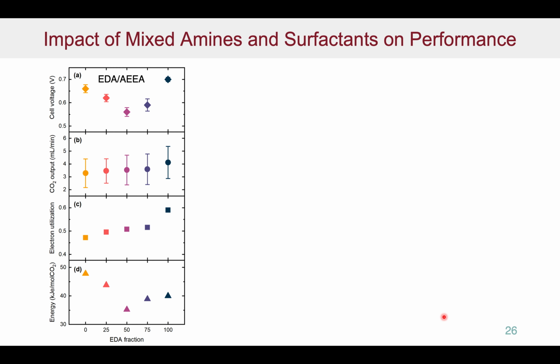We've done some more work on this since then and recognized that by modifying the solution conditions and the like, we can actually enhance the overall performance of these systems. In particular, if you use mixed amine systems, the EDA and AEEA, aminoethylethanolamine, case, with a 50-50 mixture we can reduce the cell voltage required quite dramatically. So overpotentials are reduced, which is something we'd like, and the energy consumed is significantly less as well. It's much less than the 40 kilojoules per mole.